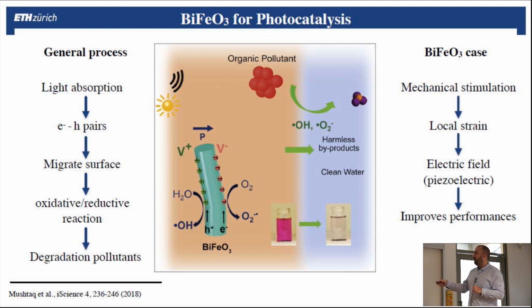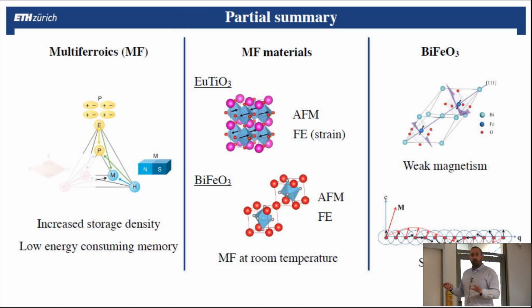they put bismuth ferrite in that solution, and they stimulate mechanically, so by applying sound waves. By doing this, it implies a strain in bismuth ferrite. And you saw that strain, just like what we saw before, will have polarization enhanced. And actually, by this strain, there is a larger electric field inside the material, which results in improving the performance of this cleaning. So that's just to show you that it's still an interesting material.